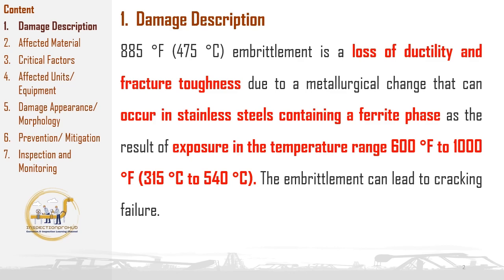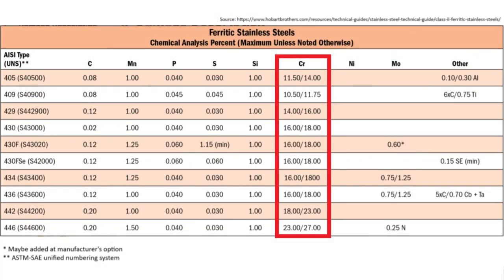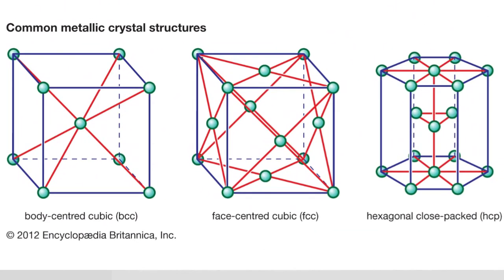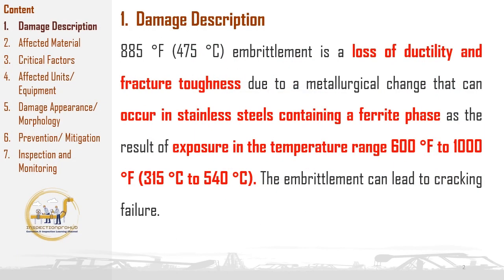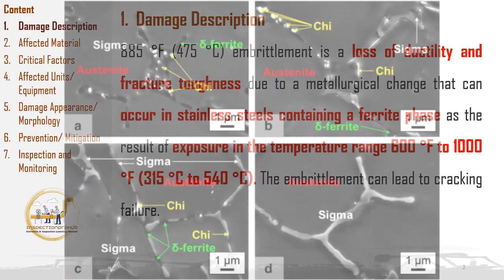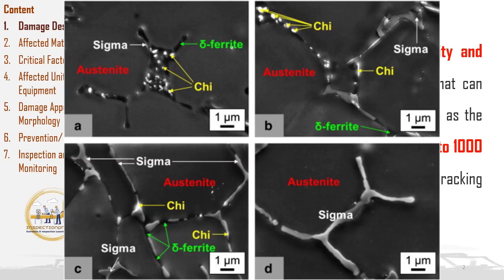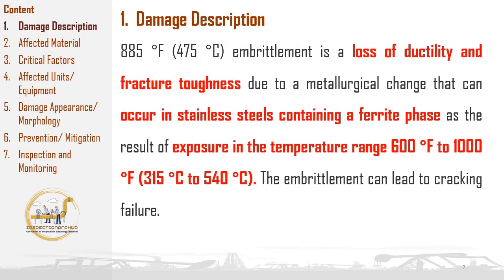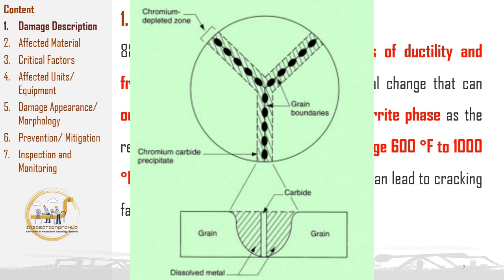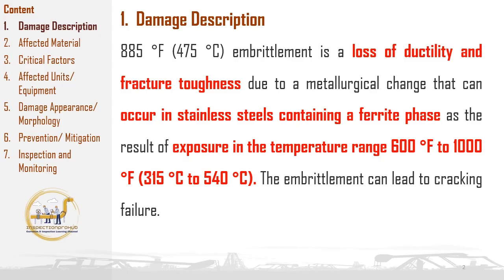Ferritic stainless steels typically contain 10.5 to 30% of chromium and have a body-centered cubic crystal structure, and when ferritic stainless steels are exposed to the temperature range of 600 to 1000 degrees Fahrenheit, certain crystalline phases, like the sigma phase and chi phase, can form. These phases are brittle, and their formation weakens the material, making it more susceptible to cracking. In addition, chromium carbide precipitation can occur at grain boundaries. The carbide formation depletes the surrounding areas of chromium, lowering the steel's overall resistance to corrosion and mechanical strength.